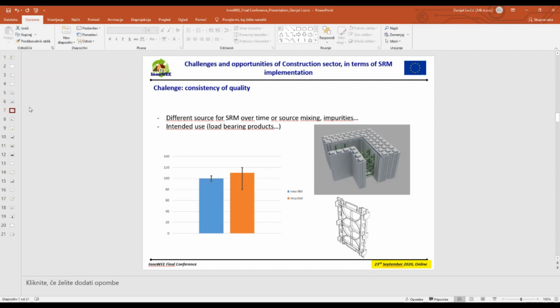One of the challenges is to have a consistent quality of SRM. The reasons for quality variations can be different, like different sources through time, source mixing, impurities. When we developed insulated concrete forms from EPS for nearly zero energy housing, the plastic brackets between EPS walls are made from polypropylene, and when we tested the tensile strength of brackets from virgin raw material, the results range was quite smaller compared to the recycled one.